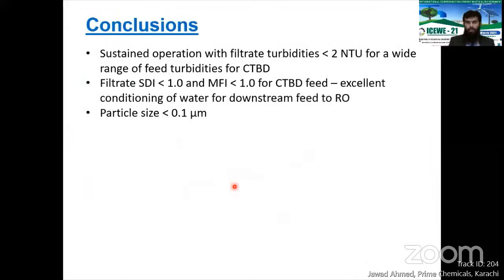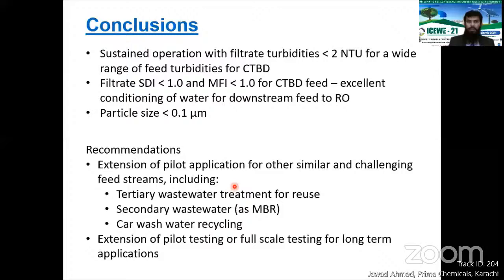So to summarize the conclusions, we found sustained operation with filtrate turbidities of less than 2 NTU for a wide range of feed turbidities. And we found SDI of the filtrate to be less than 1, the MFI value of the filtrate also to be less than 1, which again represents excellent conditioning of the water for downstream feed to RO membranes. And obviously the particle size was less than 0.1 micrometers.